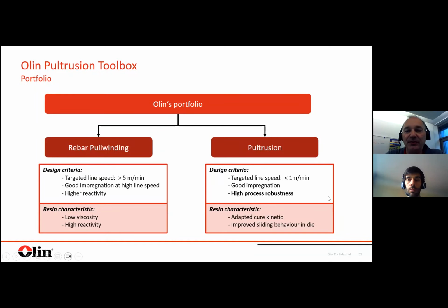So the characteristic here, more from the viscosity point of view, is on the lower side, and it should be more reactive. For pultrusion, there we are really targeting a line speed around 1 meter per minute. Good impregnation at this line speed. Here we have a little bit more freedom. Here the key is a high process robustness. As mentioned, the pultrusion system is more sensitive due to the fact that it's cured in the closed die. Here we put a lot of effort. I will not explain, but this is something which makes a big difference in comparison to pull winding. So that means that we here have a resin characteristic, an adaptive cure kinetic, to enable the control, and let's say an improved sliding behavior in a closed mold.